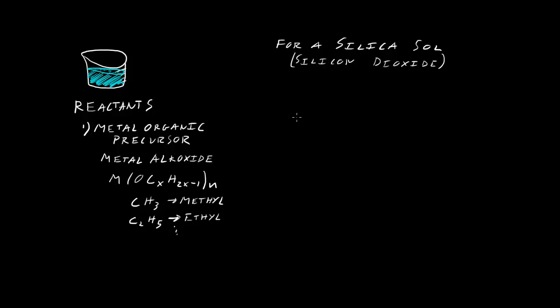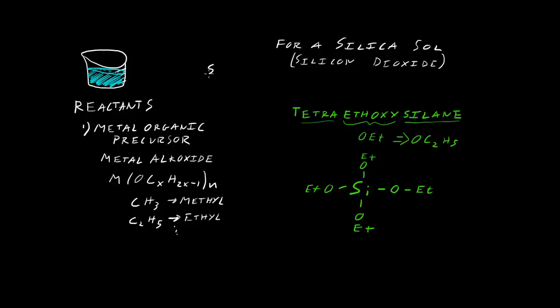If we're going to make a silica sol, so if we're making silicon dioxide gel, we're going to use probably one of the most common ones, tetraethoxysilane, abbreviated as TEOS. The silane part tells you that there's one silicon atom. Ethoxy lets you know that the silicon is attached to an oxygen which is bonded to an ethyl group, or C2H5, so silicon, oxygen, and then ethyl group. Tetra lets you know that there's four of these. That's TEOS, that's our precursor. Now our final shape that we want, our final molecule, is silicon dioxide, which is a bunch of silicons that are bonded to each other through these bridging oxygens. We're not quite there yet, but we at least have our silicon and our oxygens, so now we need to find some way to get rid of those ethyls and bond each oxygen to another silicon.